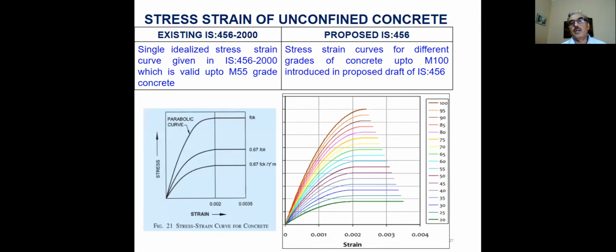Stress strain of unconfined concrete: normally in the existing code we had this idealized curve, common for all grades of concrete, with 0.002 strain at peak and ultimate strain at 0.0035. But what happens is when we go for high strength concrete, it is more brittle, as you see from these curves - these are for lower grades, and this is for the high grade.